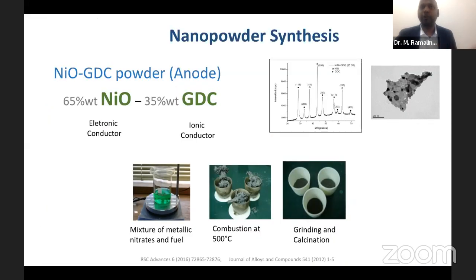That sintering we also do at different stages. For example, after fabricating the anode tubes, we have to sinter at around 1,200 to 1,400 degrees. Then after the electrolyte coating and cathode coating, we sinter again. This is not just a material; I can say that these are cells.